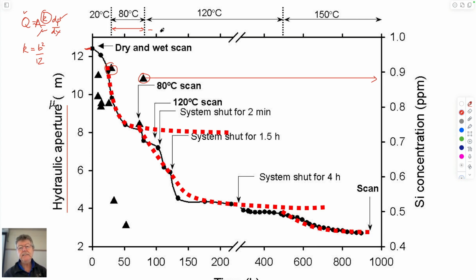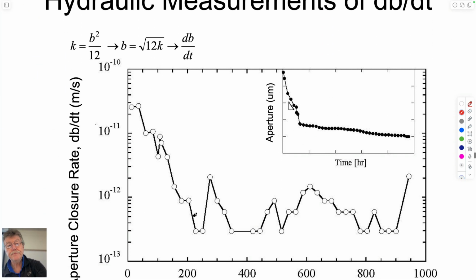And when you take it up from 80 degrees to 120 degrees, again, we're net dissolving material. We don't have readings for these dissolved components, but you get this behavior where the permeability goes down again. Then when you take it up to 150 degrees, obviously the pressures in here are bigger than atmospheric because it doesn't boil. And again, the permeability goes down. So if you're net dissolving material, you should be net increasing permeability. And we also know that porosity is equal to aperture divided by spacing. If you net dissolve and net increase porosity, you'd think that you'd net increase permeability. Doesn't happen. So something else is going on.